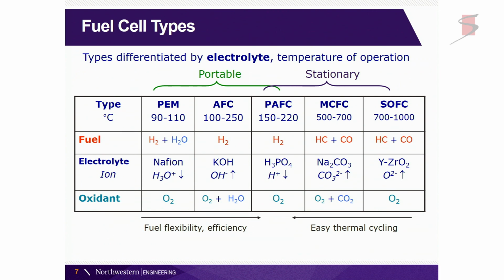I mentioned that these are transportation versus stationary power fuel cells. They're essentially differentiated by the temperature at which they operate. Stationary fuel cells typically operate at rather high temperatures, and they incorporate an electrolyte, which is a phosphoric acid electrolyte, molten carbonate electrolyte, or a solid oxide electrolyte, and then FC is just for fuel cell. And that establishes the temperature, because that's the temperature you need in order to get the ions to move through that electrolyte.